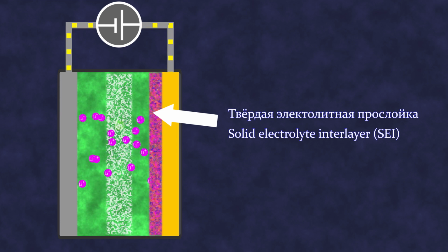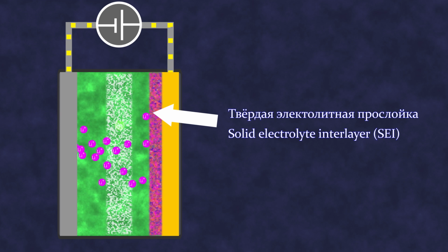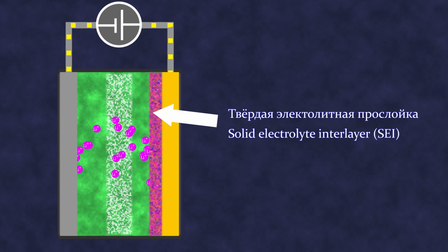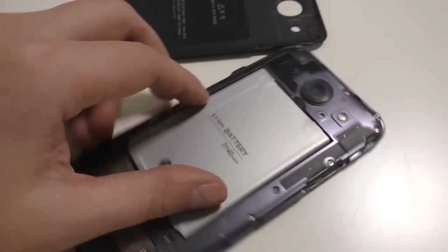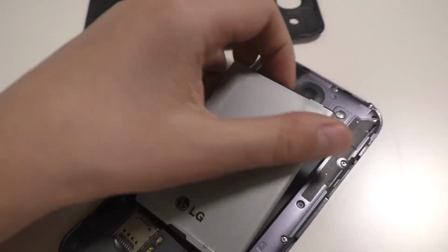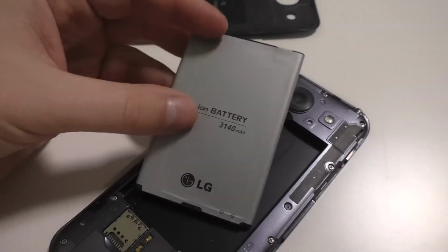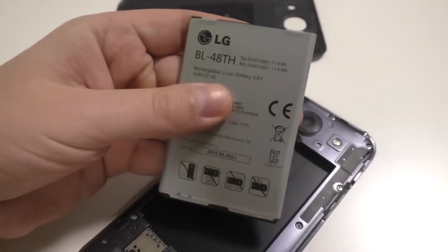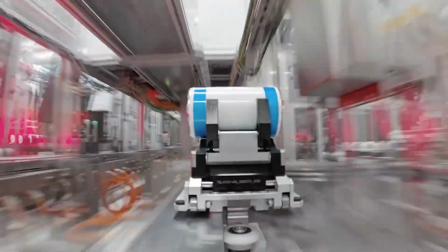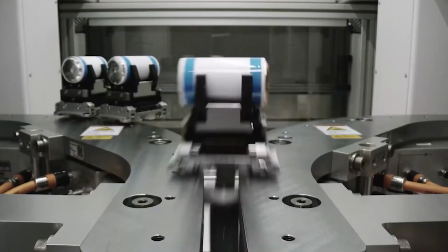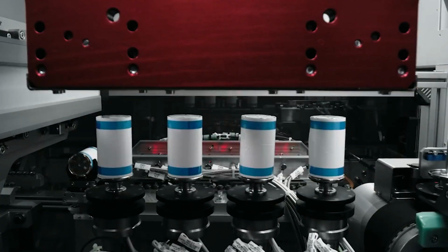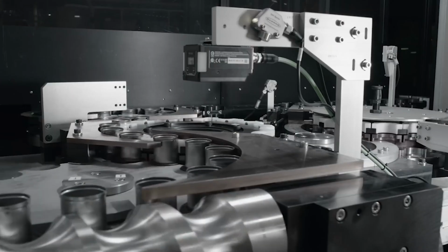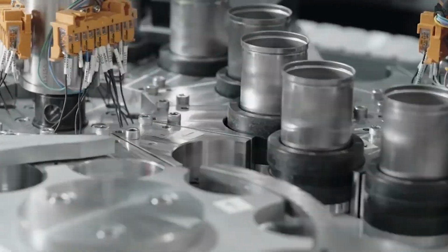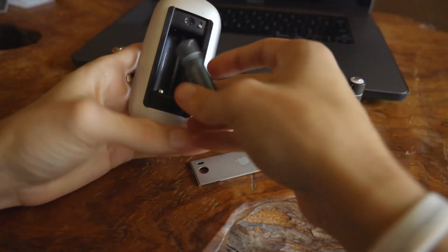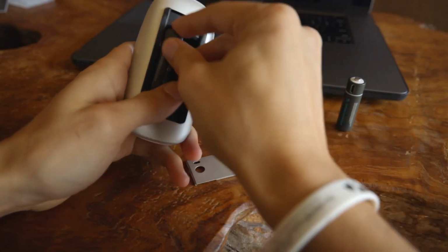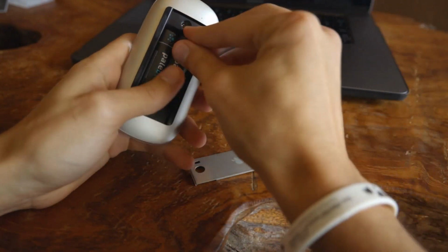This barrier allows lithium ions to pass through, but remains impermeable to electrons, preventing their direct contact with the electrolyte and all related negative effects. It was precisely to allow this layer to form that the first lithium-ion batteries needed to be fully charged and then discharged, repeating the procedure several times. Today, with the role of SEI in battery operation well understood, this is no longer necessary. Scientists have calculated the ideal parameters for the solid layer, and it is intentionally created at the final stage of battery manufacturing. So modern lithium-ion batteries already have the SEI when you first take them out of the box.